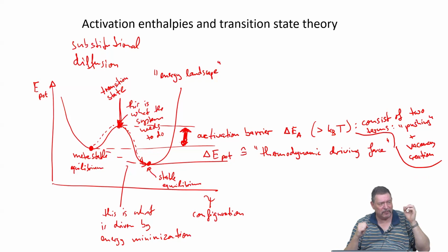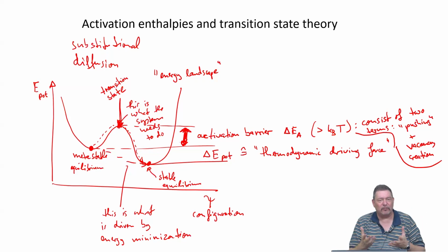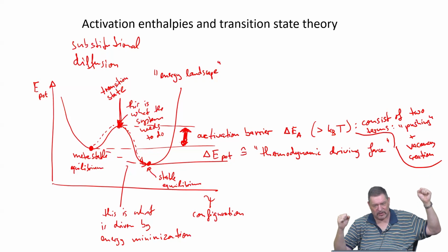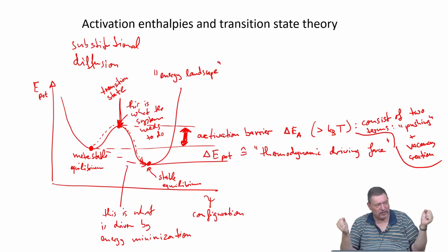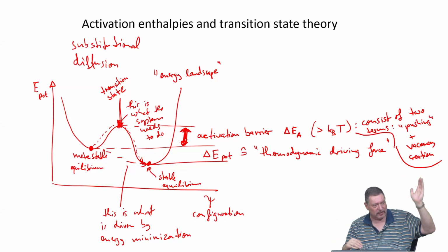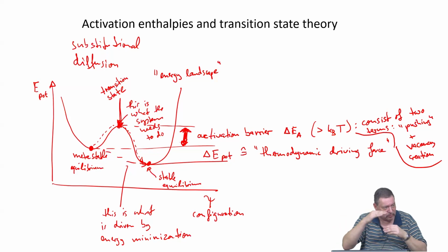So this is very important when you see these potential energy landscapes in papers. Often they are just a crude picture of what people think might be happening, but they often don't realize that whenever you have a directionality in the process, like applying any type of field, you have to consider that the energy landscape is changed, and that with the gradient you basically tilt and shift the landscape so that any processes go downhill more easily. So you change the activation barrier heights.